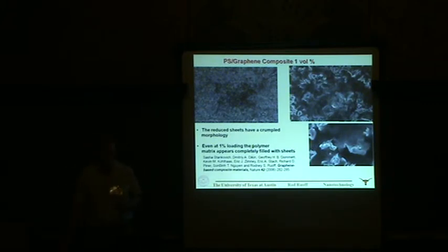So it's believed the reason for the difference, we had thought about this in my group, is, if you look at other choices like crossed fibers, you sort of touch at a point, not really, of course, it's an area. But same thing with nanotubes. Nanotubes have not really imbued polymer matrix composites with good thermal conductivity from an engineering point of view. There's been a lot of good physics done. And again, they're crossing at a very small contact area. But graphene can overlap graphene and probably have more effective phonon transfer in one sheet than another.